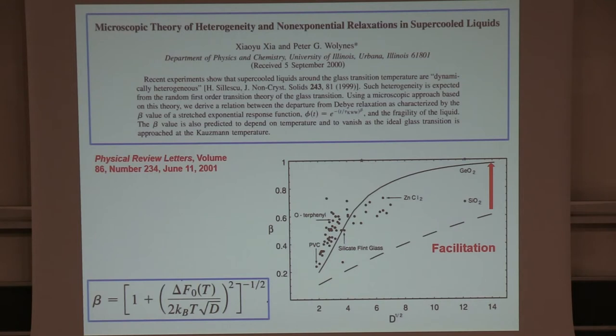Okay, now, I said that there's this diversity of states. And the theory that I described here so far is almost just exactly like nucleation. Where does the diversity of states come in? Well, we said that it comes in at the non-exponential relaxation of quantities. These usually follow what's called a stretched exponential law. And the stretched exponential relaxation has been measured for lots and lots of things. It's difficult to measure because it really involves curve fitting and so on. But it's been measured for many of them.